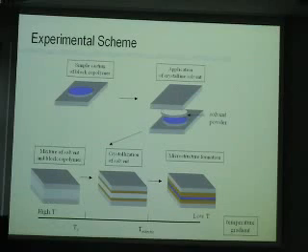We just cover it with a cover glass and then increase the temperature above the melting temperature of the benzoic acid, produce the homogeneous liquid, and then crystallize the benzoic acid. Just the process is done. Finally, we can characterize the block polymer structure.